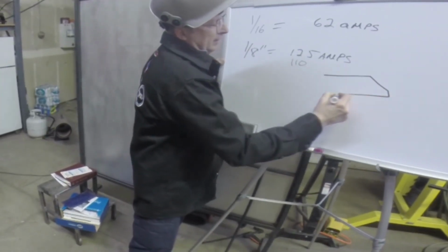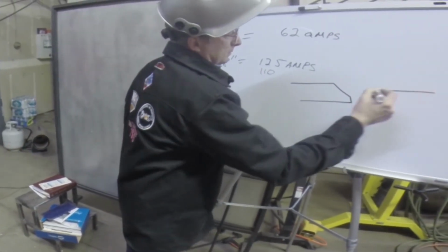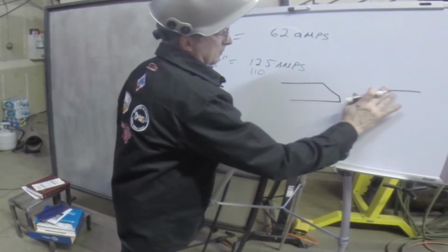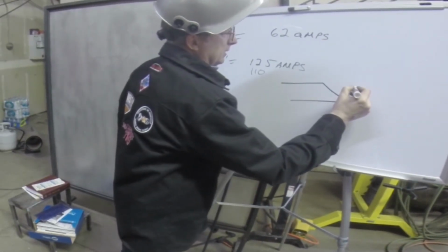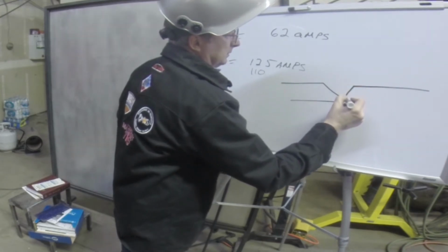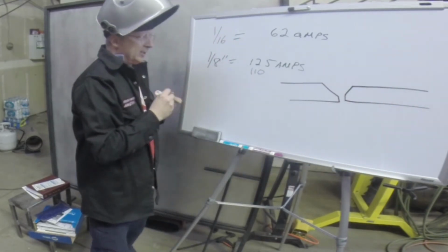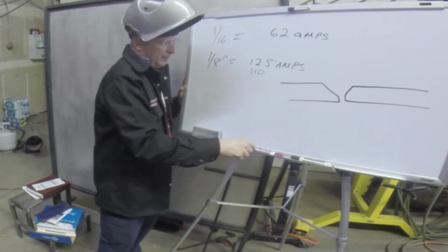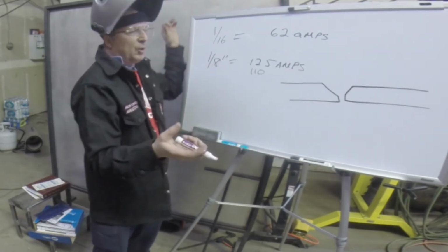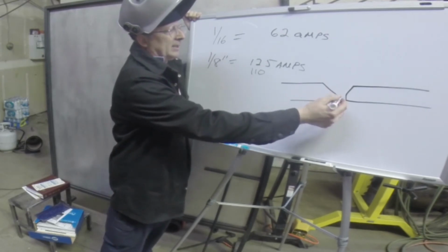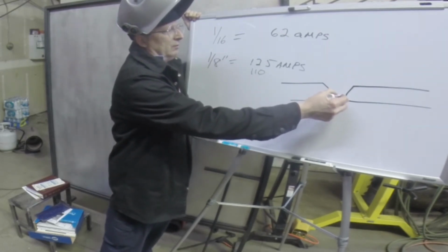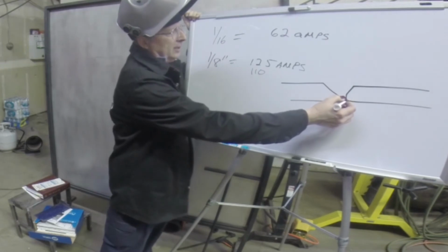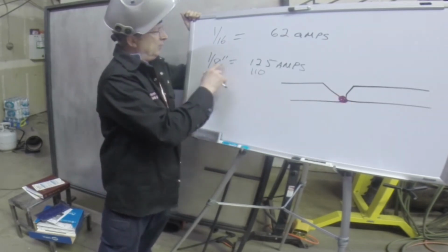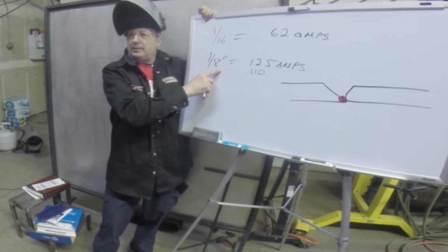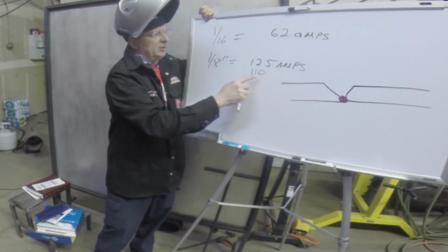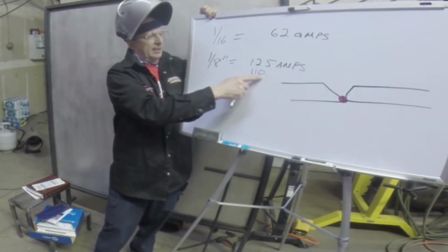Let's say we have a butt joint here. Not the world's best art, this should line up. We've got high-low already and we haven't even lined the slates up yet. So that's our butt joint right there. This could be a pipe or a flat plate. The first thing you want to do is, the most important weld in any joint is your root pass. So you do your root pass in here, and if you get good penetration, you tie it in like that. When you're doing, say, 1/8 inch 7018 or 6010 on your root pass, you usually want to drop this down to say 110.